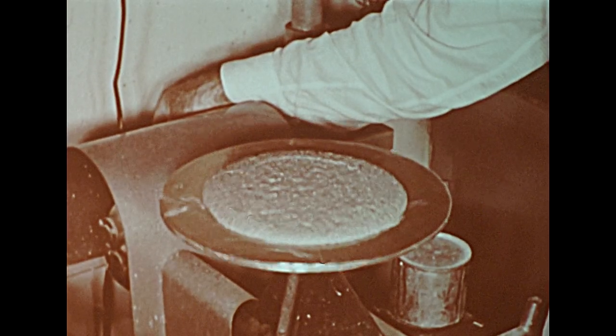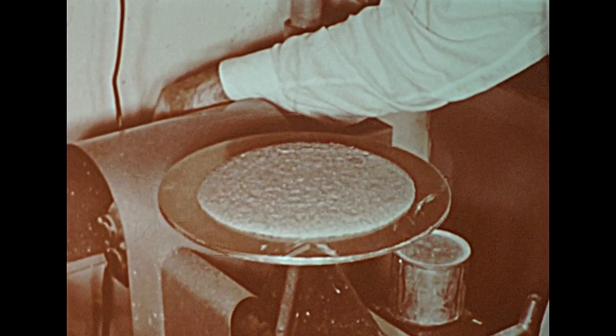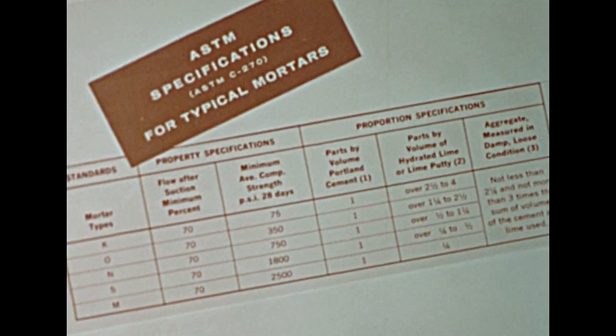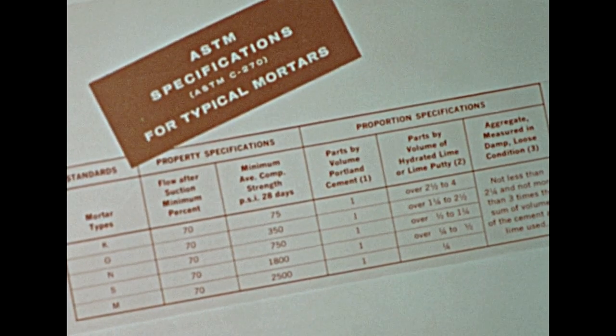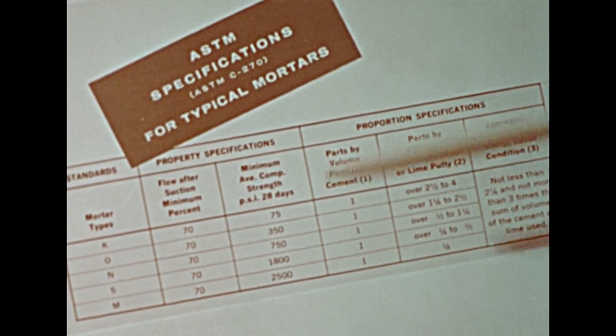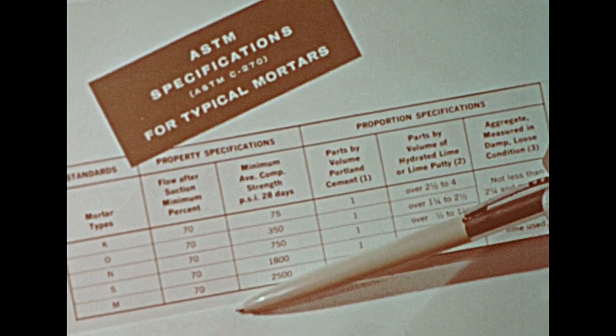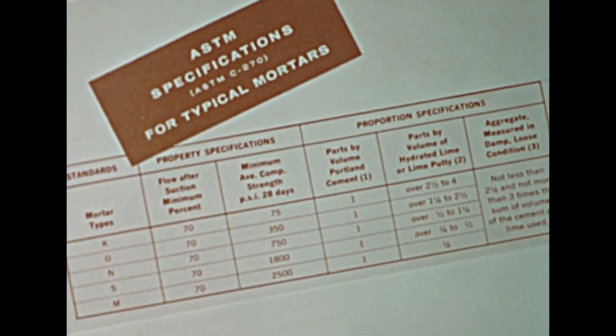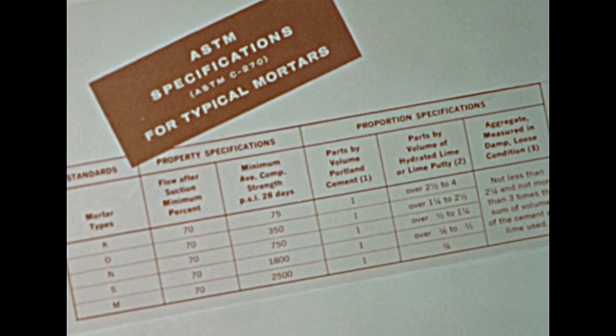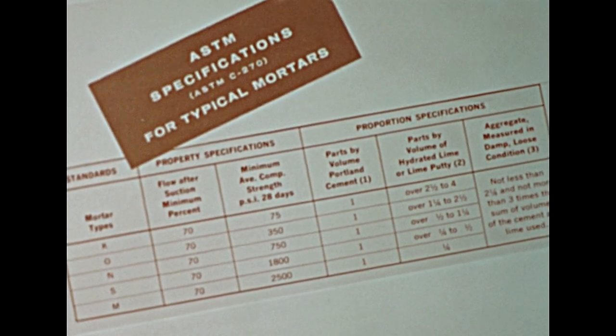It's interesting to note that according to National Bureau of Standards and the American Society for Testing and Materials specifications, minimum flow permitted after suction is 70%. The ASTM test you have just seen proves that high lime mortar runs well above this minimum.